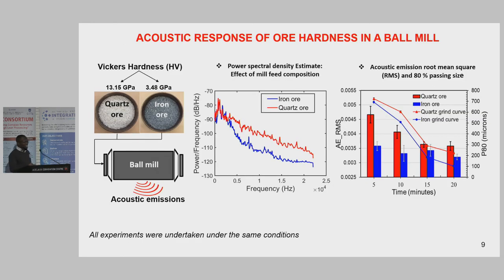This result also presents two different ore hardness properties, where we look at the model quartz and the iron ore and their acoustic emission during grinding in a laboratory ball mill. The two ore hardnesses produce distinct acoustic energy under the same condition. The acoustic emission of the model quartz happens to be higher at different frequency bands as compared with that of the iron ore. This is also reflected in their size reduction profile, such that as you grind over time and the particle size reduces, the mill acoustic also reduces.